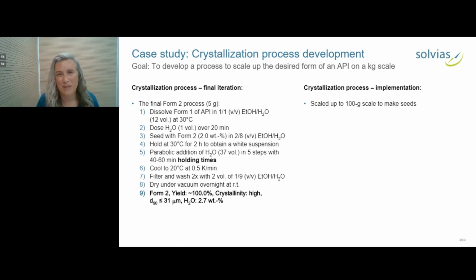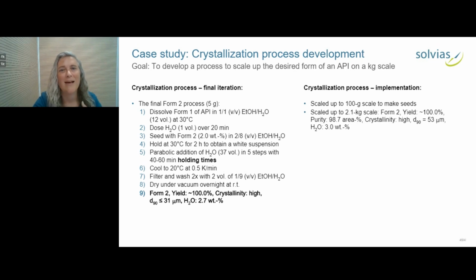We could then scale this up to the 100-gram scale in a 5-liter vessel to make seeds, and scaled it up to the 2.1 kilogram scale. Again, got excellent purity and yield. Particle size was a bit larger than we'd like, but that could be mitigated by micronization. And the process was basically the same as developed in the lab.